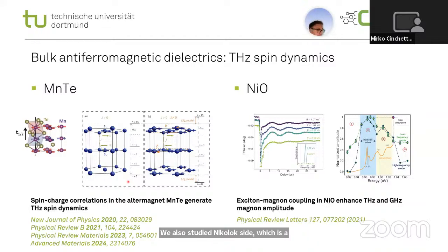We also studied nickel oxide, which is a Mott insulator, and this material has a very sharp excitonic feature in the optical absorption spectrum. And this exciton is actually coupled to a magnon. And what we have been able then to show is that if you excite nickel oxide in resonance with this exciton magnon, you can enhance the amplitude of terahertz and gigahertz magnons in this material.